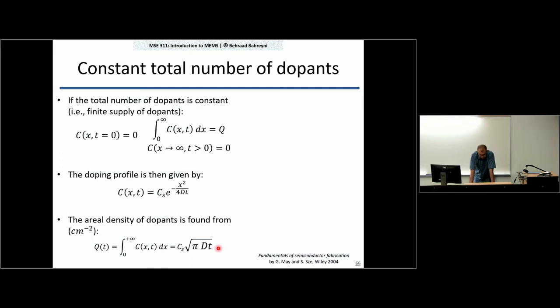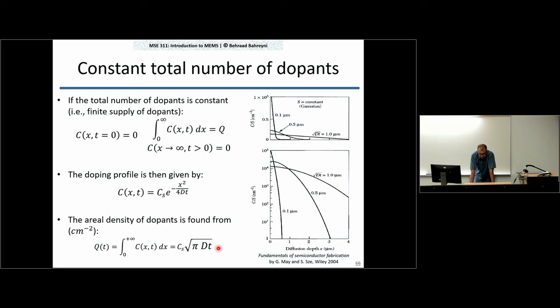Okay. Now, unlike the previous situation where we had a constant surface density that decreased as we went further into the substrate, in this case your surface density at the top will also change, right? So if you wait, you're moving the dopants from here, and you're redistributing them into the rest of the substrate. So your surface concentration will start to drop as you do the diffusion over longer and longer times. But essentially, it's still a diffusion process. Because of a different boundary condition, you get slightly different profiling.